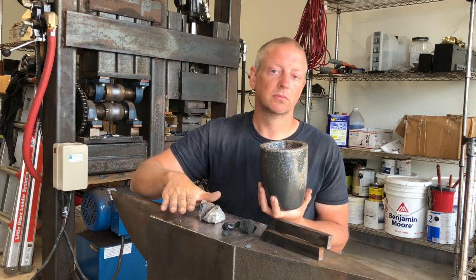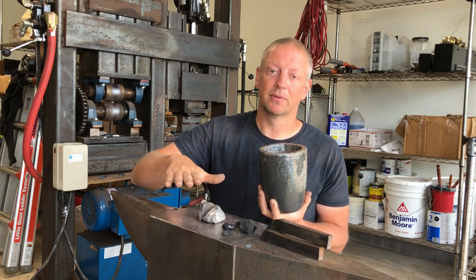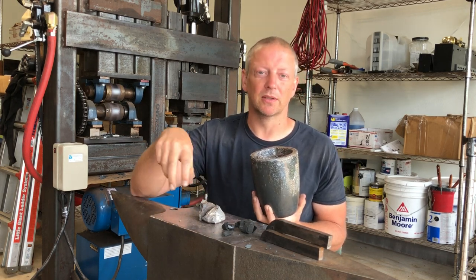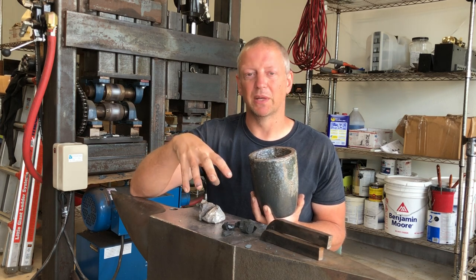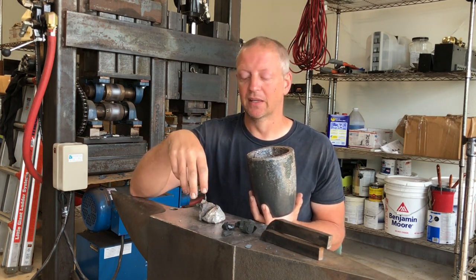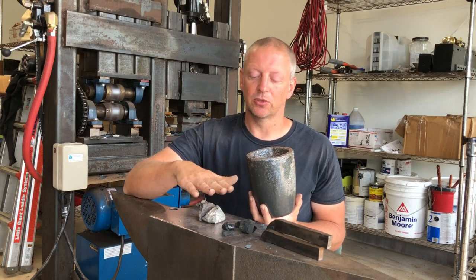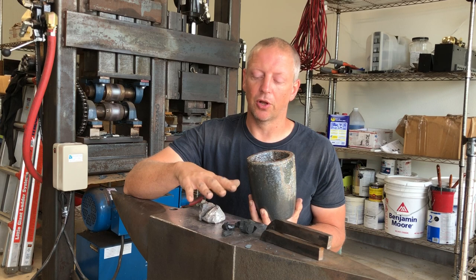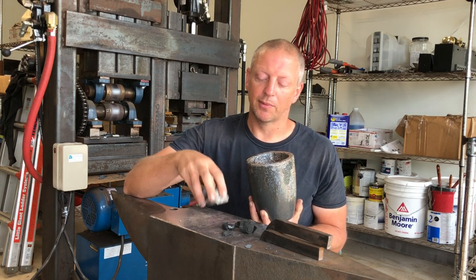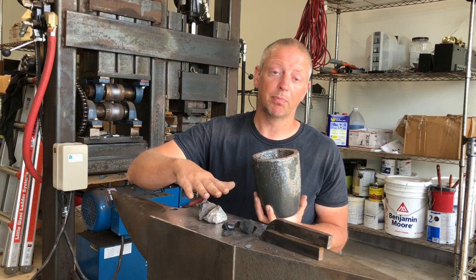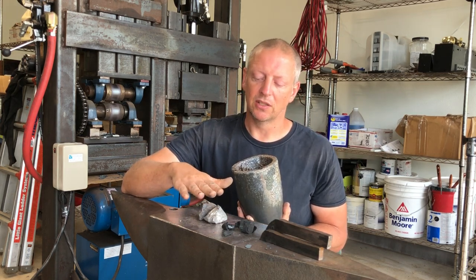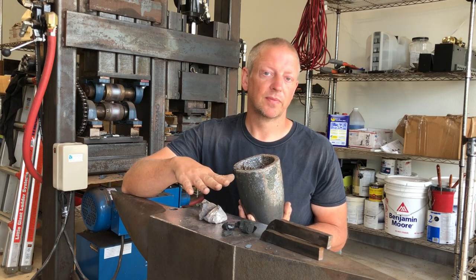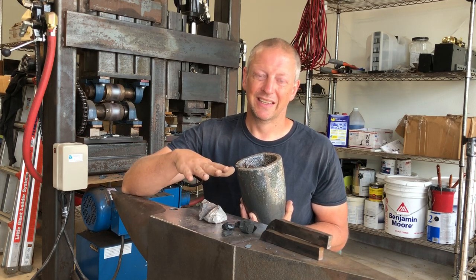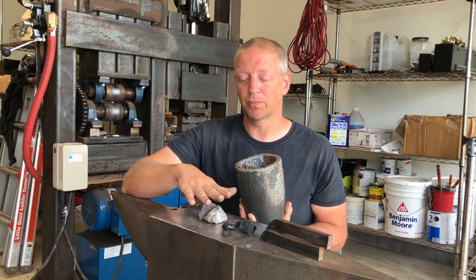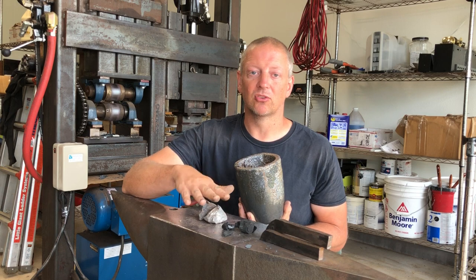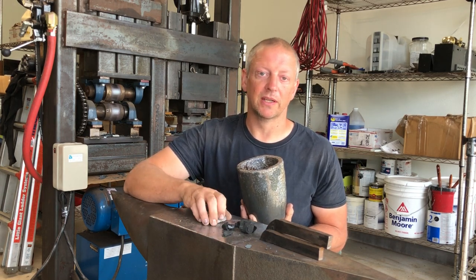If you put your pig iron in the bottom and your mild steel on top of it, your pig iron is going to melt early on, leaving a gap, because your mild steel will probably kind of forge weld itself together, essentially. It will be hot enough. I believe it's called sintering in industry. But you'll basically create a bridge of your low carbon material, and your high carbon material will just melt away, make a nice puddle. You'll get a gap which will fill with slag, and then you'll have your low carbon material sitting above it. You're going to have to achieve a high enough temperature to melt that mild steel in order for it to incorporate into that puddle.